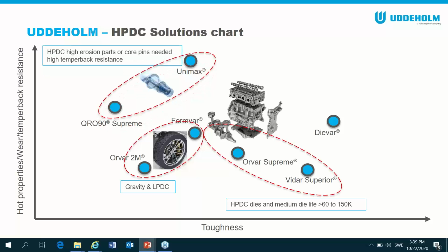If we look at Unimax and QRO90, you can distinguish the two. You can say Unimax is for high erosion, high wear applications, and QRO90 for corings. Very, very good for corings, particularly if you use the pre-hardened version, QRO90 HT.